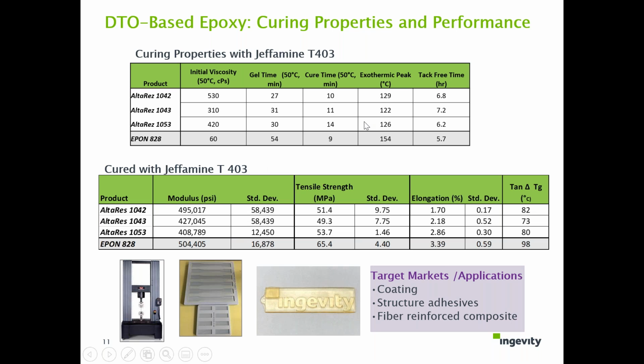When you look at the peak exotherm temperature, our DTO epoxy has about 36 degrees lower peak exotherm temperature compared to the benchmark EPON 828. In some applications, the lower peak exotherm temperature is a benefit, for example syntactic foam or tooling applications. People are really looking for a relatively lower peak exotherm temperature, but with the material completely cured.